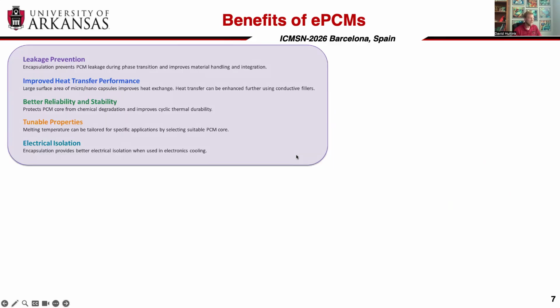And so what this allows us to do is really multiple things, right? So we no longer have the issue of leakage because the shell itself contains the ePCM or the PCM material so that it cannot escape. But the shell can also help to improve the heat transfer performance because the shell itself has improved thermal conductivity. But it also is delivering in a small particle, which increases the rate of that phase transformation because you have more surface area of engagement with the surrounding temperature environment.